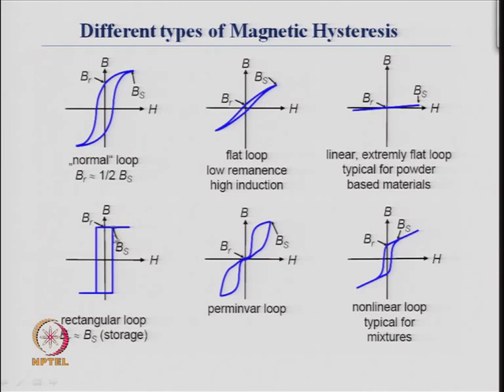So, this is a rectangular type of loop, this is a normal loop, and this is very good for storage. You can apply a particular field, and immediately all the dipoles are aligned. You apply a field in the opposite direction, all the dipoles will get misaligned and you will get a resultant flux density of 0. So, quick switching can occur in this kind of system. Here it is slightly slow because it varies with the magnetic field, it does not change suddenly. In this case there is very low remanence, although the induction or the magnetization is high.